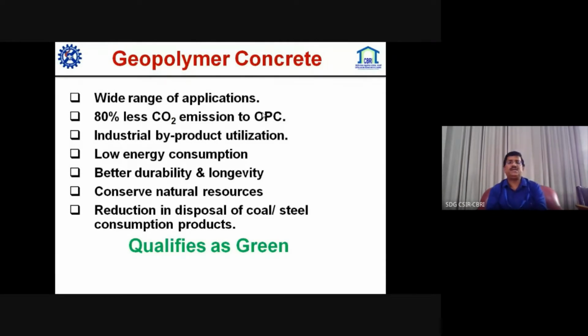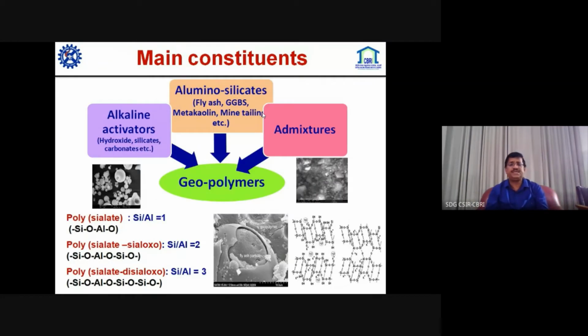And it directly utilizes main byproducts, that is, fly ash, ground granulated blast furnace slag, red mud, and others, which are rich in silica and alumina content. Red mud is also very good. People are working very nicely on making geopolymer binders. So it has very low energy consumption and durability. We have worked very extensively on this at CBRI, and on its chemistry, its utilization in the civil engineering field and others, which I am going to take up.